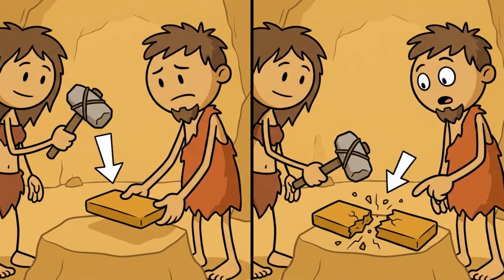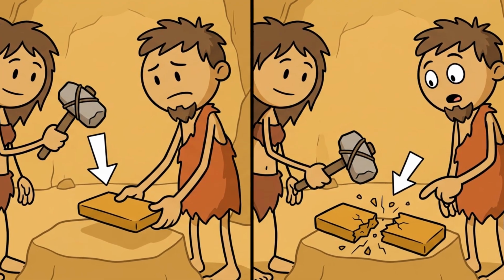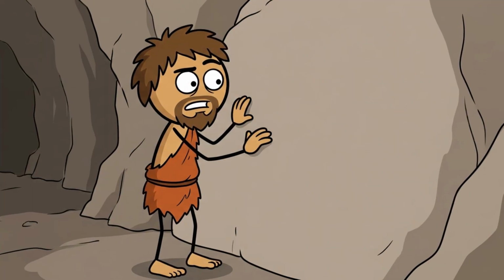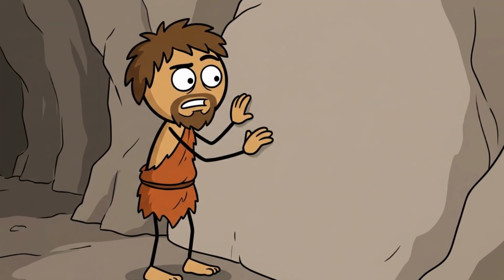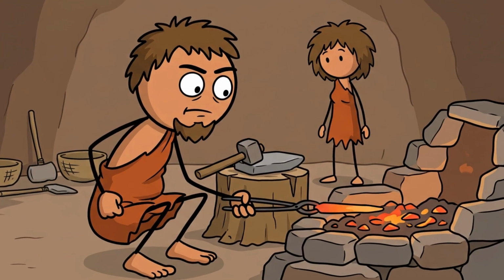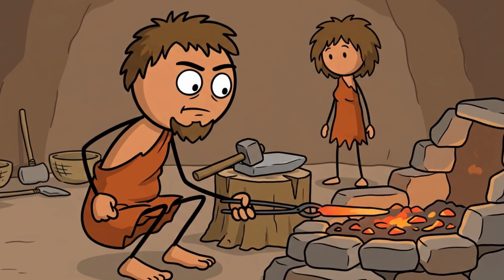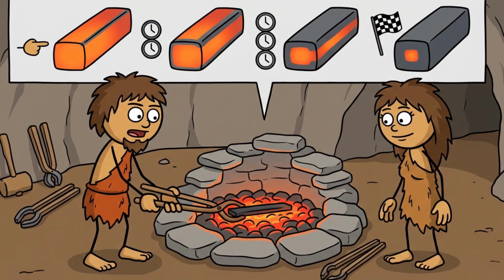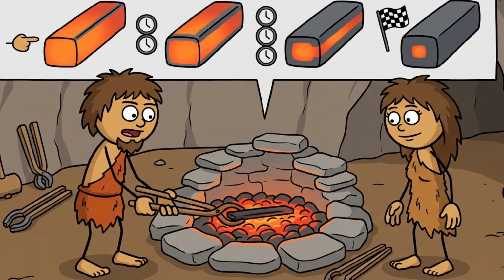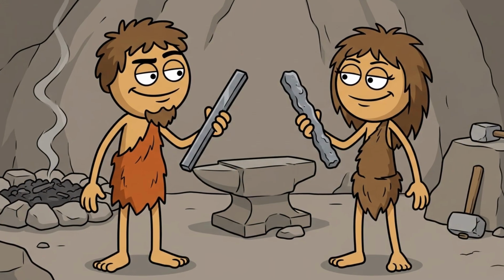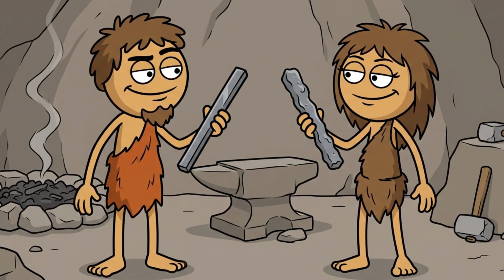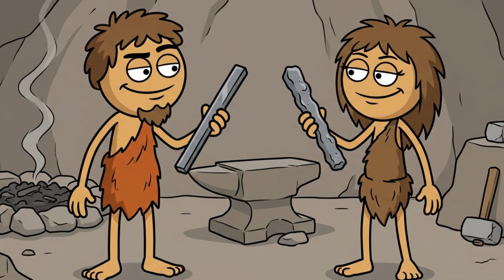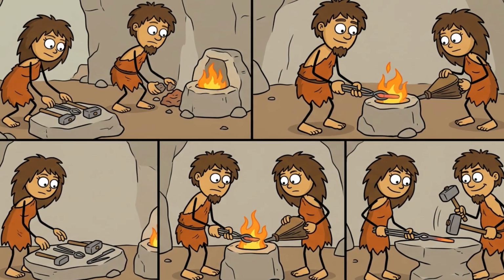And then there is the last step, the one that finally makes iron worth all of this. Steel is iron with a small amount of carbon in it, between roughly 0.5% and 1.5%. Below that, it stays soft. Above about 2%, it becomes cast iron, hard but brittle and will crack rather than bend. Getting into that narrow window was not a recipe anybody wrote down. It came from the forge itself.